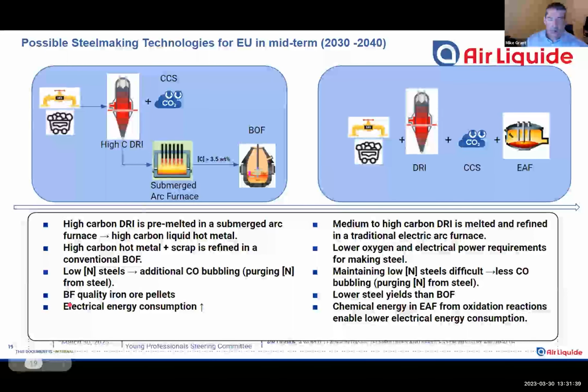The other thing, of course, is there's a shortage of DRI grade pellets, which are very high iron content pellets. And this method would enable you to use blast furnace iron ore pellets, which have a higher slag volume. And because the submerged arc furnace is a reducing environment, we don't have the problem with FeO in the slag. The higher the slag volume, the more FeO you lose, so your yield goes down. Nevertheless, in this case, you don't have the benefit of chemical energy like you do in the classical electric arc furnace. And so we can anticipate a higher energy consumption in the submerged arc furnace. Nevertheless, you can benefit from this CO purging of the nitrogen that will be dissolved in the steel.